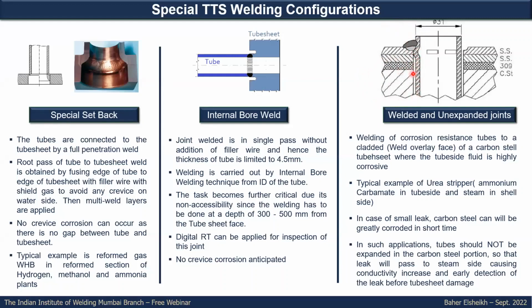But while you don't have expansion here, you have a gap, meaning once you have an issue in the tube, the leak will pass easily to the shell side, and the parameters monitored on the shell side, from the conductivity, ammonia traces, or whatever might come from the tube side to shell side, you can easily detect. Then you can take the proper action, usually by isolating the unit and shutting down the plant to take action before having an aggressive attack to the tube sheet.